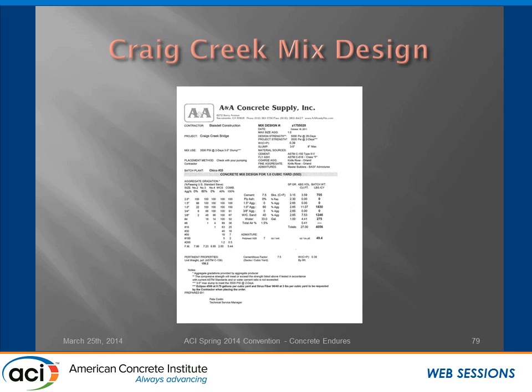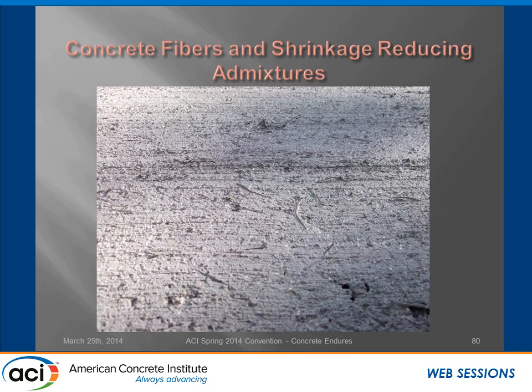We wanted to see basically if we cook the concrete and heat hydration and get it really hot, see what would happen with the fibers and the shrinkage reducing admixture. You can see these are macro fibers. They're the long fibers, and it actually kind of looks like it needs a shave after you're done. We ended up grinding and grooving for multiple purposes on this project.